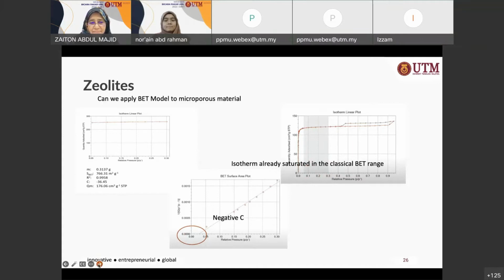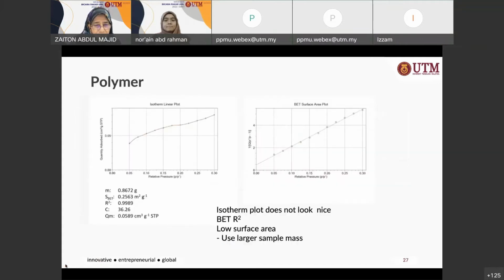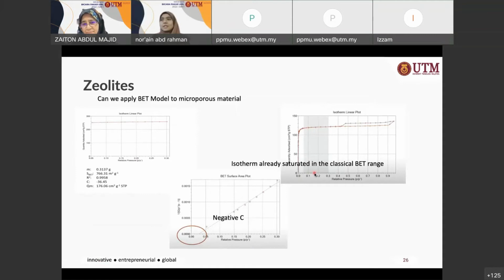So in this particular case, you might want to run the sample at a lower pressure. Or what they did for Micromeritics, they ran it on another instrument which caters for the microporous range. We're just showing you that if you do a microporous material, whereby the BET equation is not applicable, you're going to get a negative C. And if you look at this here, this is already the saturation limit. So you need to run probably at a lower range rather than this range.